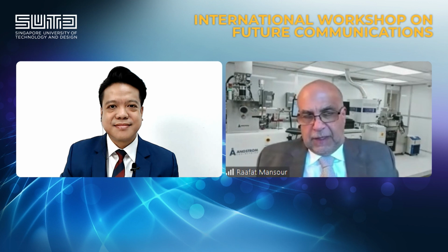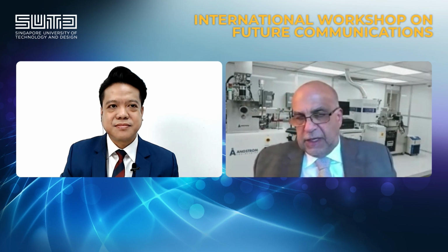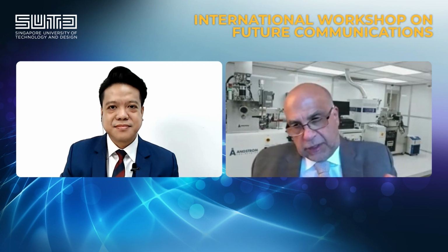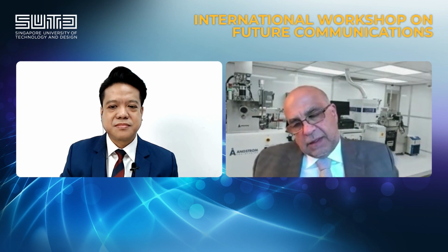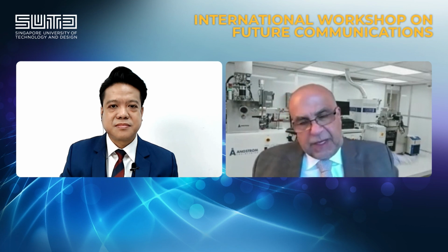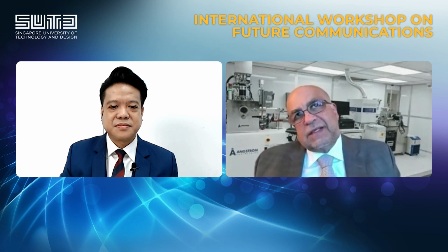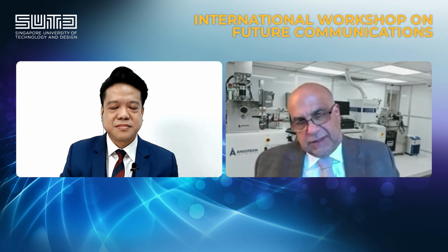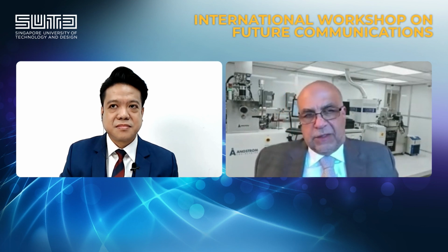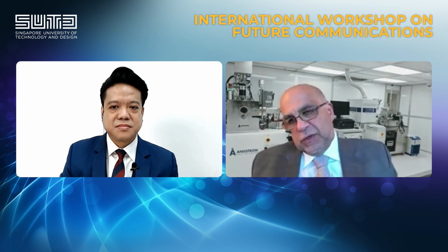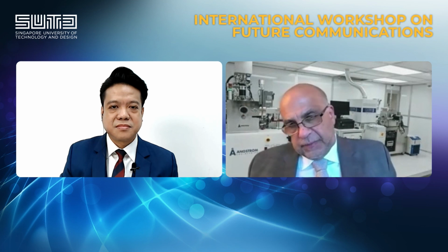Yes, indeed. Ourselves, we are using GeTe material. Many research groups are also using GeTe. Tower Semiconductor uses GeTe material, but there is an organization on the West Coast that is using GST, a material from the same family. The advantage of this material is that the requirement on the heater design is a bit less than if you use GeTe material, because the temperature required to switch from one state to another using GST is lower.